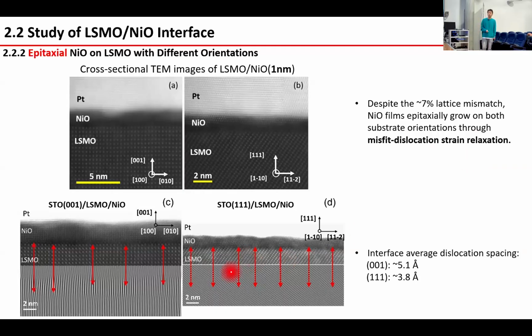And we also obtained the filtered Fourier image as shown below. It shows the red arrows indicating the dislocations, and we calculate the interface average dislocation spacing at around 5.1 angstroms in the 001 orientation, and also 3.8 angstroms in the 111 orientation.